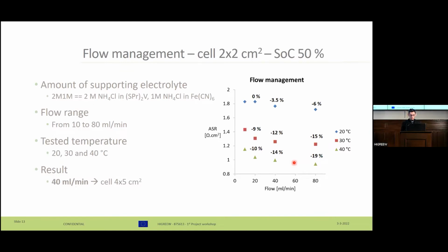Before the experiments on the large cell, we have to find the best flow rate. And on this graph, you can see the decrease of inner resistance of the cell with given temperature and range of flow rate. We found that 80 milliliters per minute is not good due to some pressure and energy losses. So we want to test in other experiments a flow rate of 40 milliliters per minute.